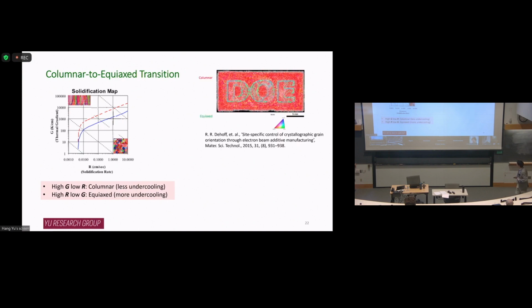And this was demonstrated by Oak Ridge National Lab a few years ago. They did E-beam additive manufacturing of, I think, a nickel alloy, to show that you can manipulate your processing parameters to control the G/R ratio, so you can get some areas of columnar grains and some areas of equiaxed grains, right? The red means a strong 100 texture, and that's columnar grains. And the greenish or non-red color is more like equiaxed grains with random texture. They can control that, so they can make a pattern like a DOE, showing that.